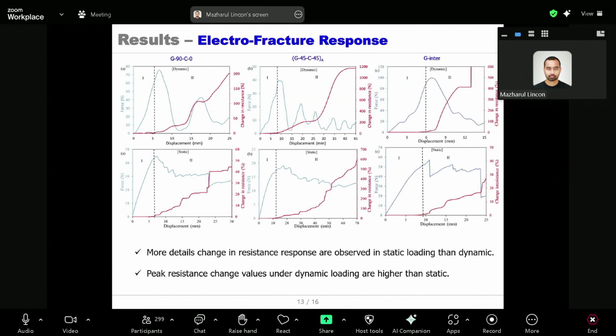Now, the primary difference between dynamic and static experiment is time. In this dynamic experiment, we consider 40 millimeter crack growth of the specimen. To create this 40 millimeter crack growth in dynamic experiment, it happens in only 7 to 10 milliseconds. On the other hand, in the static case it takes 7 to 12 minutes. It's a considerable time difference.